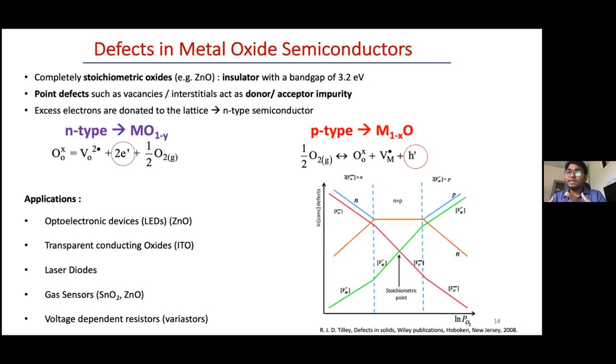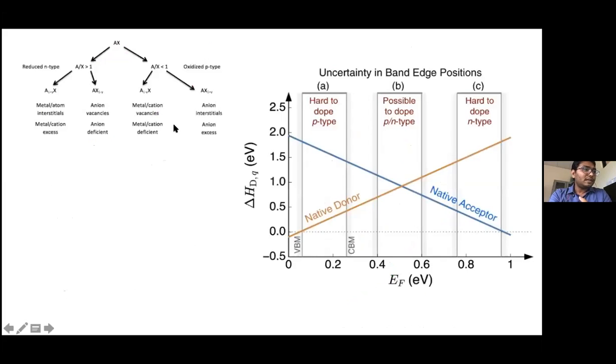So many of these oxides are either metal vacancy rich or oxygen vacancy rich. Correspondingly, they will have either majority hole type conduction or majority electron type conduction. You can see that there is an AX shown here, where A is, let's say, the metal, and X is your anion, which is an oxide. If one of them is higher than the other, then it reduces to either n-type, or in the opposite case, it reduces to p-type.